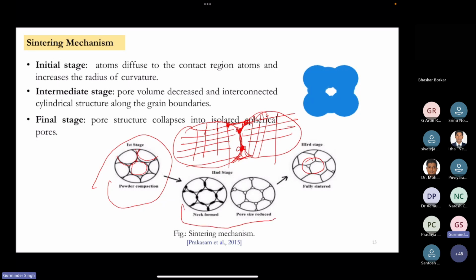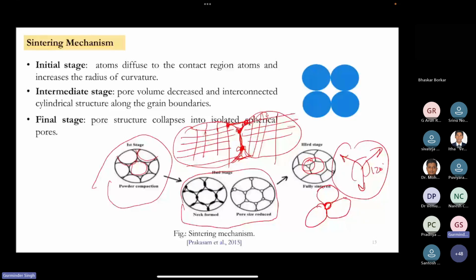So neck formation and pore size reduction is the second stage of the sintering mechanism, and it will later end up making a spherical pore. So why is it a spherical pore? Because, let's see, if you have three balls together, it will later make a spherical pore, which is called the final stage of sintering. And because it has an equilibrium of energy at around 120 degrees, it will give you a complete equilibrium of energy, and it will not grow in this particular direction, and it will make a spherical shape. That's why it's not always 100% dense. This process gives around 99.9% density.